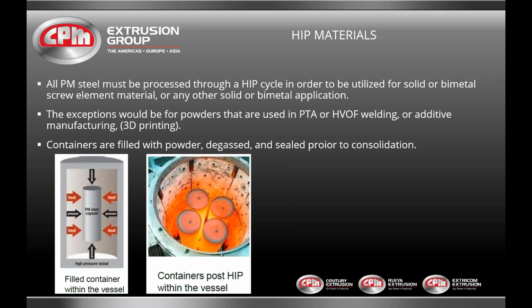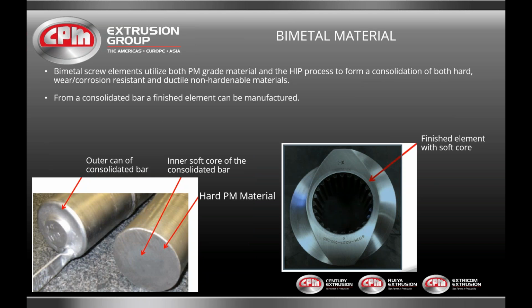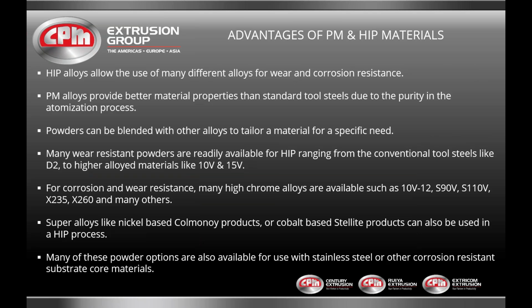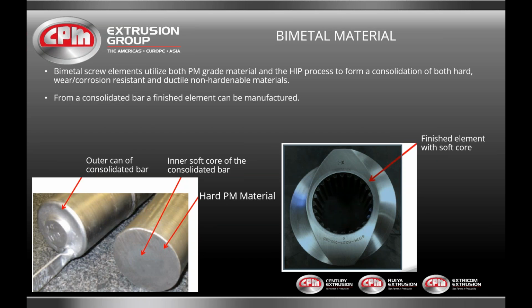For HIP, the containers are filled with powder, degassed and sealed prior to consolidation. Bimetal materials, the bimetal screw elements, utilize both PM grade material and the HIP process to form a consolidation of both hard wear and corrosion resistant material and the ductile non-hardenable metals. From a consolidated bar, a finished element can be manufactured.